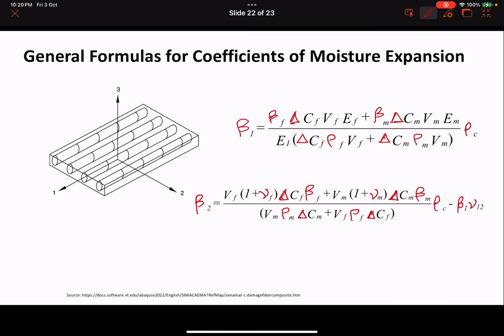Similarly, you have moisture expansion. Here what happens is the specimen is made and placed in water, and the moisture expansion strain is again measured using strain gauges in 2 directions. So that's how you get beta 1 and beta 2. You can see actually in your book the graphs are not given, but it's the same process as temperature change, only this time we are recording the weight that the specimen incurs and then strains, of course. So from there, using the graphs, using empirical models, elastic models, you get these very complicated looking equations for beta 1 and beta 2, where the moisture absorbed by fibers, moisture absorbed by matrix, the densities, the fiber volume fractions, Poisson's ratio in the second direction, everything matters.